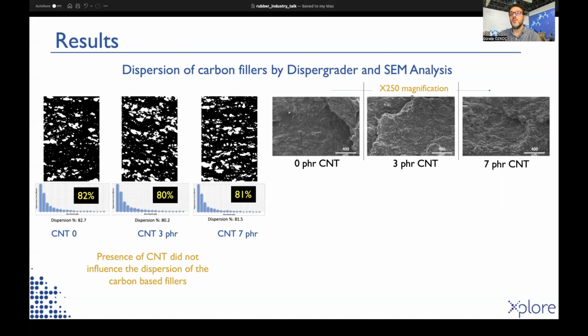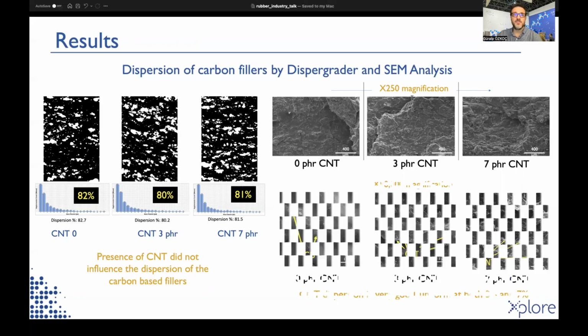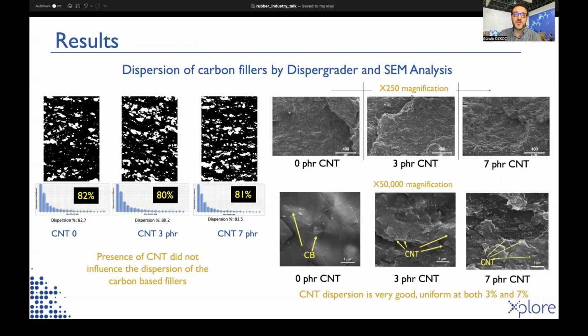The presence of carbon nanotube did not significantly influence the dispersion level of carbon black. However, carbon nanotubes are not visible at these magnifications. At 50,000 magnification, we can observe the carbon nanotubes individually, but still the carbon black particles are not distinctly visible. In addition, any aggregates of carbon nanotube or carbon black are not visible at the nano level as well. These results show that the microcompounding resulted in a homogeneous filler distribution in 3 minutes of mixing at both micro and nanoscale.